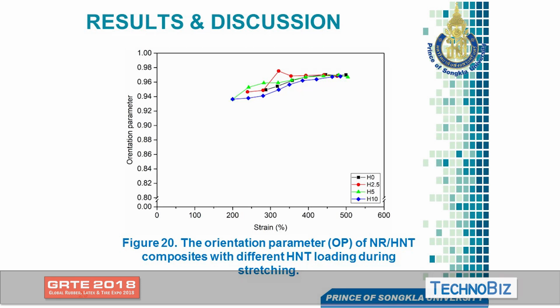This figure is about the orientation parameters. Basically, this result is not quite significant. But for your information, normally if the number is towards 1, that means the orientation is anisotropic, in the same direction as the stretching. Once the number is below 0 or negative, that means it's opposite, which we call perpendicular, the opposite direction of the alignment. But once the number is about 0, that means it's isotropic.